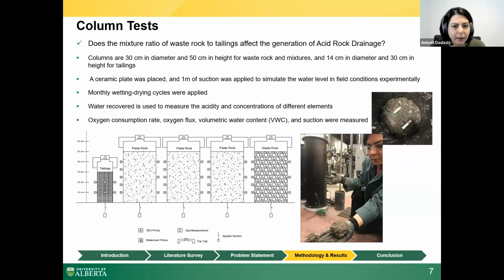When we were building the columns, we applied 1 meter of suction below the columns to simulate the water level in the field. In typical conditions in the field, the phreatic surface is 1 meter below the surface, and the minus 10 kPa creates unsaturated condition in the material, and it allows investigating the geochemical behavior of the mixture under the unsaturated condition.